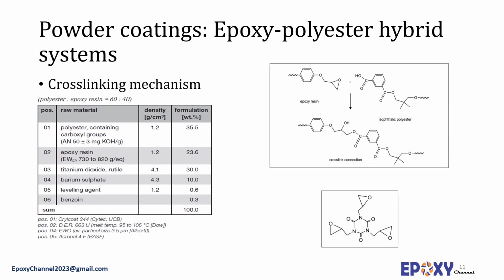The cross-linking mechanism has been depicted here, and the esterification catalyst can be phosphine, phosphonium salts, tertiary amines, and organic salts of heavy metals. Temperatures between 140 and 200 centigrade are employed for stoving in hybrid systems, and the preferred application method is electrostatic spraying. These systems provide a balanced property profile, more flexible, harder, and more weatherable, which makes them suitable for exterior coating applications. However, the level of corrosion protection and chemical resistance is not as outstanding as that of pure epoxy powder coatings. A typical formulation of these systems has been provided here.